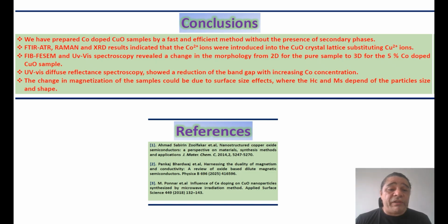UV diffuse reflectance spectroscopy shows a reduction of the band gap with increased cobalt concentration. The change in magnetization of the samples could be due to surface effects, where the coercive field and the saturation magnetization depend on the particle size and shape.